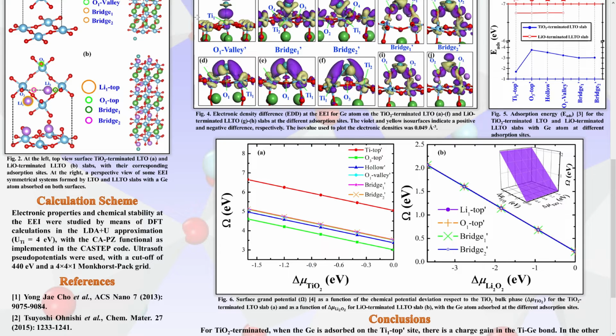In Figure 6a, it is observed by calculating the grand potential that the most thermodynamically favorable surface is the one where germanium is initially placed at the oxygen top site for the case of the titanium dioxide termination. For the case of the lithium oxide termination, Figure 6b, we find that all structures obtained after structural relaxation have the same probability of forming.